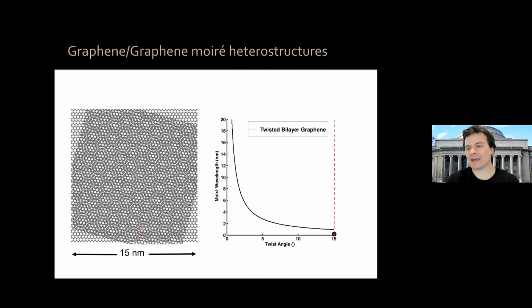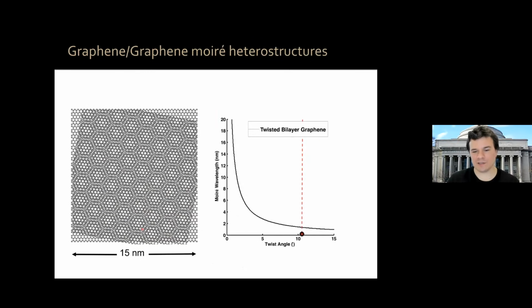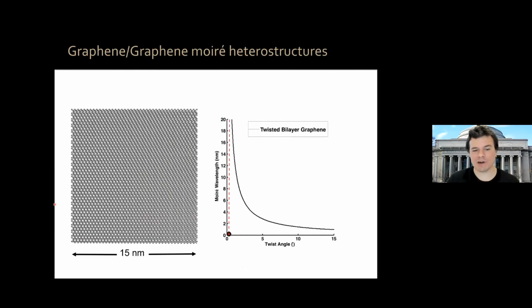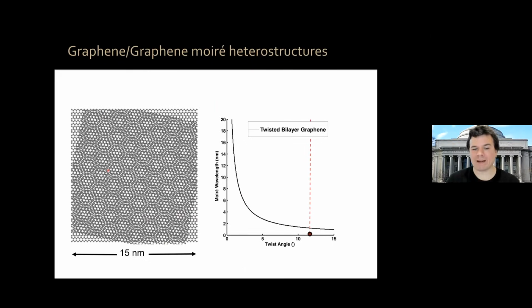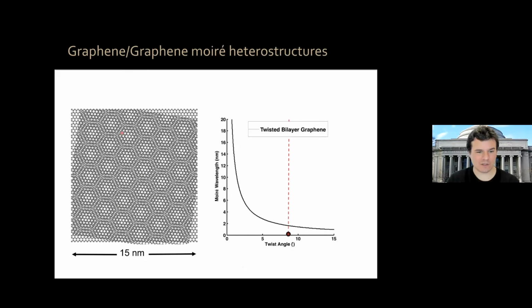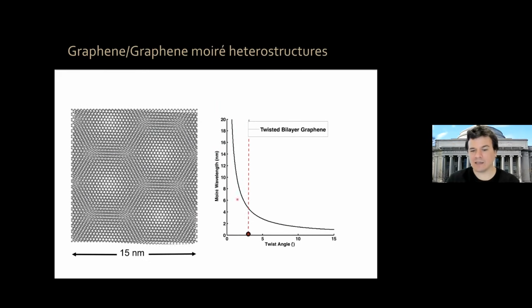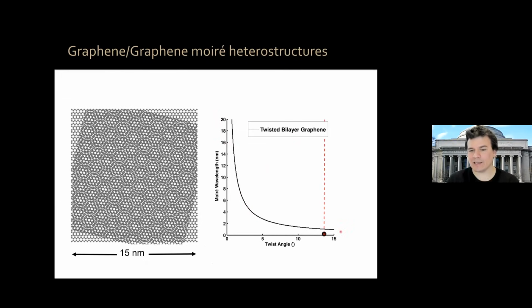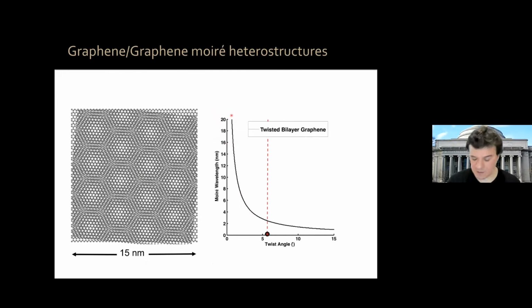Okay, so now what happens if you put graphene on top of graphene and you rotate, okay? As I mentioned earlier, a Moiré pattern forms, and the Moiré wavelength, the distance between these soccer balls that you see on the screen, depends on the twist angle, okay? It can get all the way to infinity because these lattices are identical.